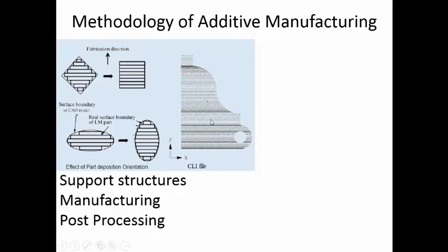So usually we say that in additive manufacturing processes, the components are anisotropic in nature, unless you are doing some secondary processing. If it is a metal, if you are able to completely recrystallize it, then we'll say that it is isotropic. Otherwise usually they are highly anisotropic in nature, which means in different directions the material will have different properties.